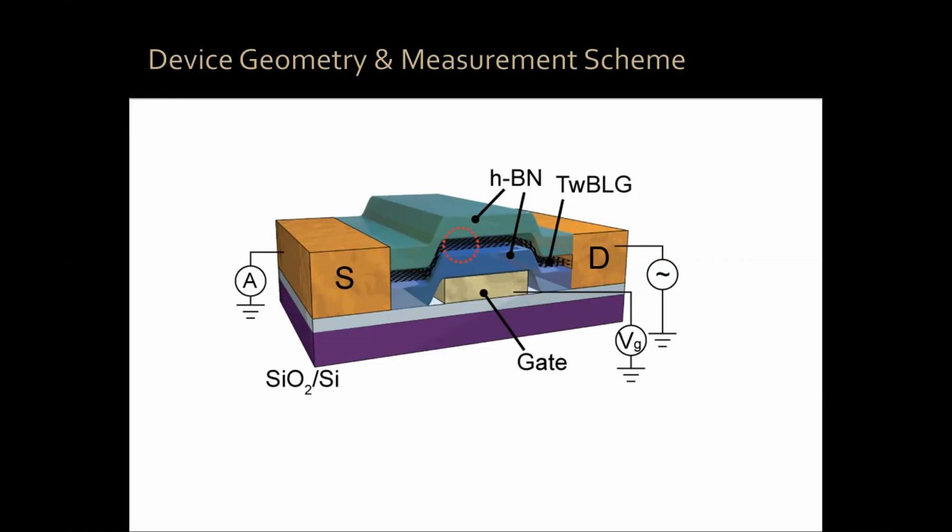I will show tomorrow. We do now magic angle pentalayer graphene, with five layers twisted. Then we have an eight or ten stacks process there. So it requires patience, graduate students, but it's doable. But my question is, does this bilayer graphene see all these processes? No, because it's embedded in the hBN. The bilayer graphene is happy there, not seeing all the polymer lithography, resist, etching, all those things. So it is going through the process, but it is not experiencing it because it's isolated by the hBN.